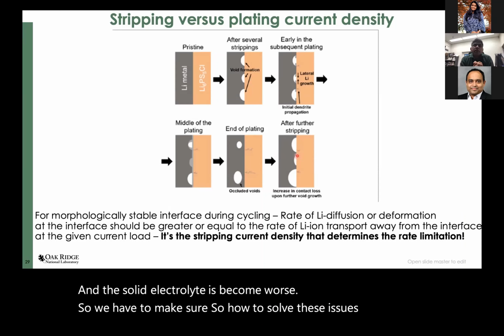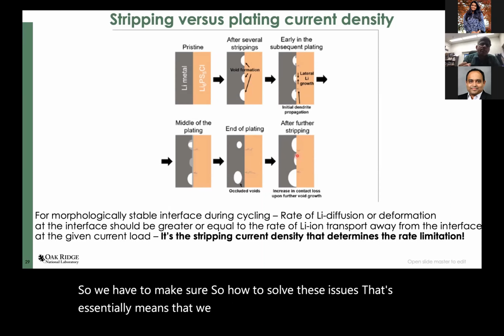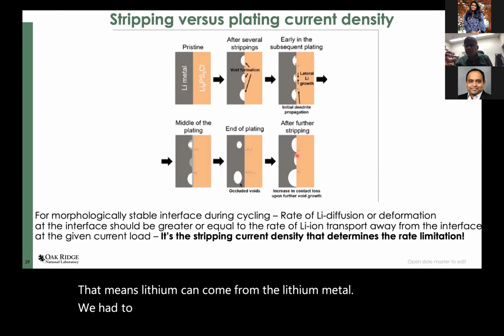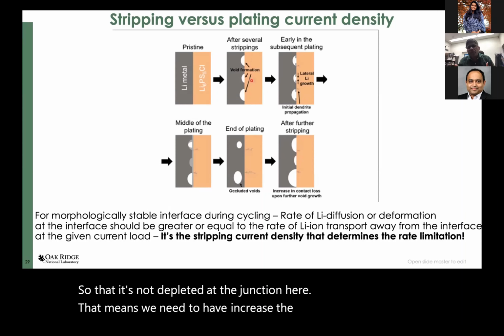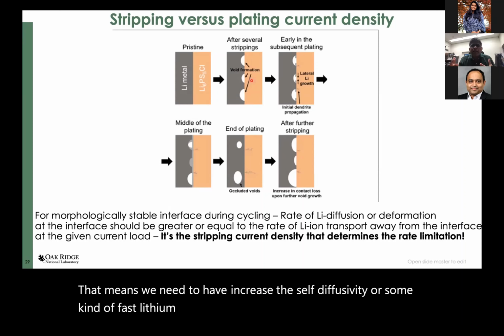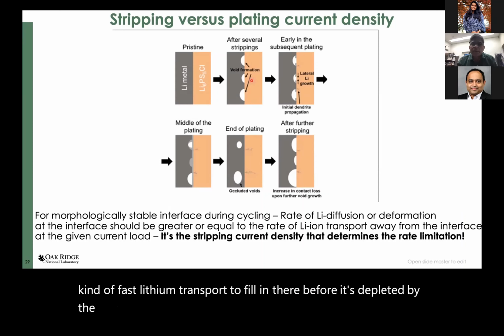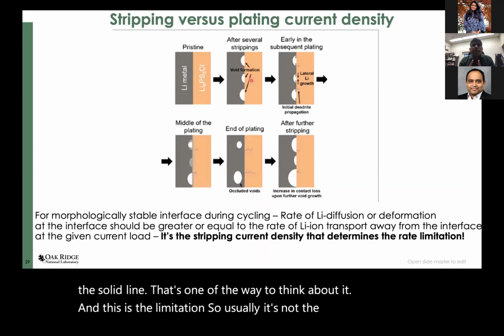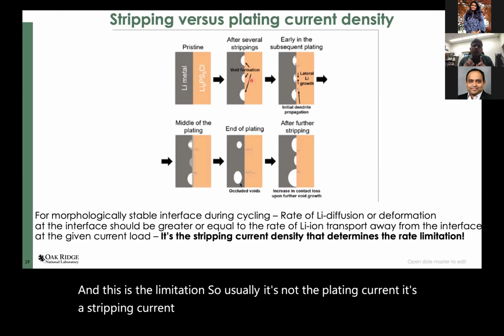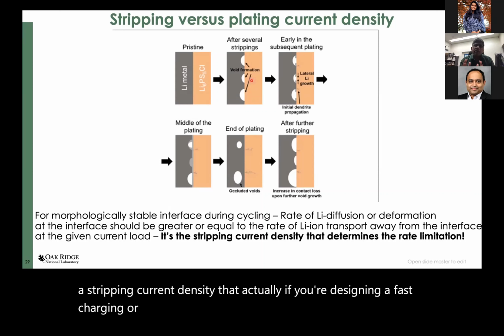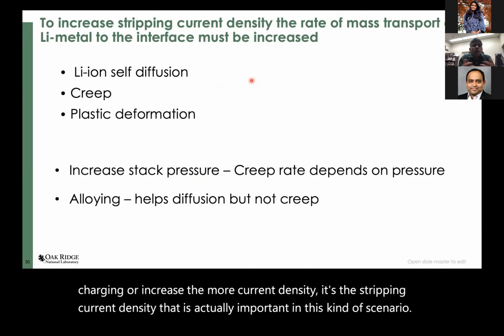That essentially means that we are taking out lithium at a finite rate. That means lithium can come from the lithium metal. We have to pull this at a faster rate so that it's not depleted at the junction here. That means we need to increase the self-diffusivity or some kind of fast lithium transport to fill in there before it's depleted by the solid electrolyte. That's one way to think about it. And this is the limitation. So usually it's not the plating current, it's the stripping current density that is actually important if you are designing for fast charging or higher current density in this kind of scenario.